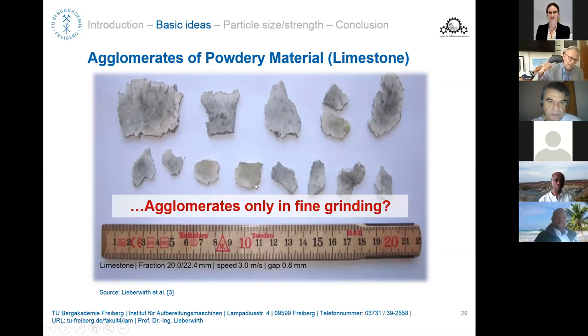So you think back about the steps of comminution, and at the very end, once you have achieved the full compression of the material, and the particles start supporting each other, you have more elastic deformation than really comminution. So at a certain point, and this is usually said in the literature, 80% solids in the space in the crushing gap, then you don't achieve more comminution. And if you think about what happens then, you find confined bed comminution happens in many cases where you wouldn't even think about it. So these nice agglomerates here of powdery material, in this case limestone, were not produced on an HPGR, they were produced on a flat-face double roll crusher.